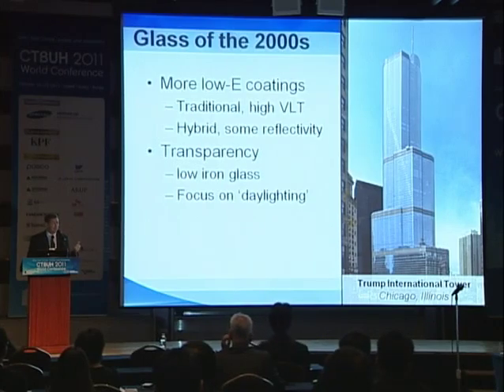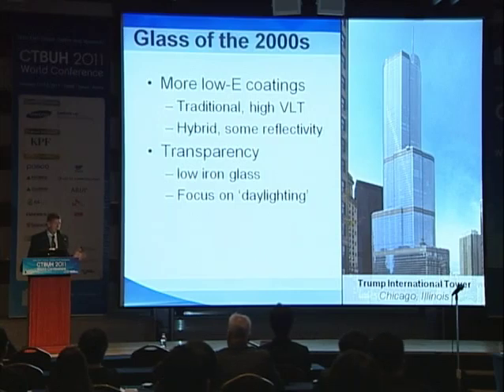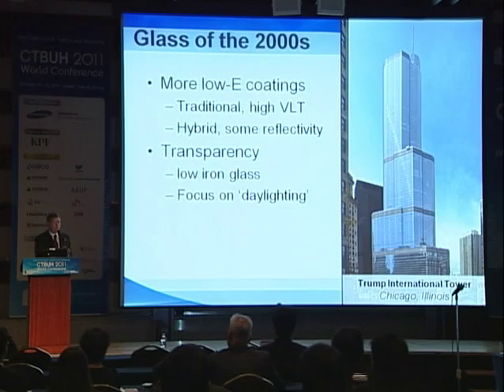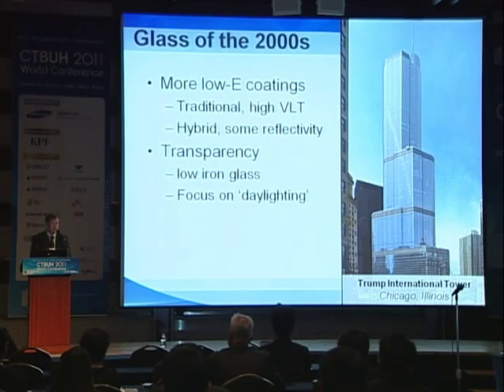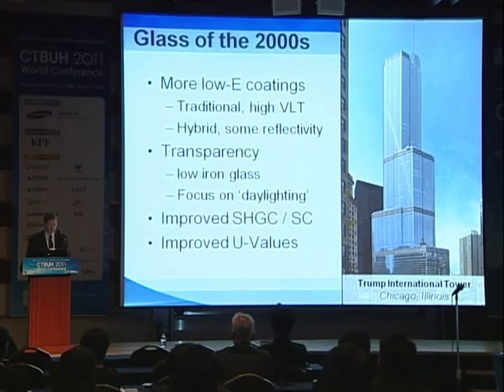And as I talk through some of these things, we also saw a huge increase in the use of low iron glass materials. Typically, the base common denominator for most insulating units is clear glass. However, as we started seeing the influx of various low iron glass materials, it became the product of choice. What essentially it did is you took the iron content out of the glass. So as you take the iron content out of the glass, you're getting more transparency. You're reducing the effectiveness of the glass, so it required more performance from the coatings. But you also got a purer look at the coatings themselves. And again, in the 2000s, we started seeing that improvement in terms of solar heat gain coefficients.